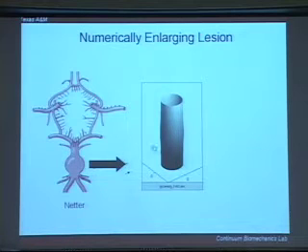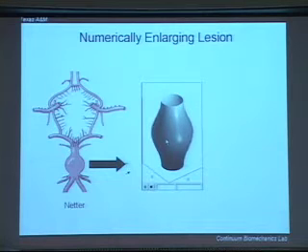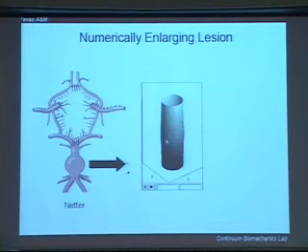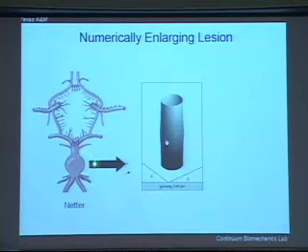So if this video will work, again, this is an academic exercise where we're looking at an idealized case where we initially remove elastin from the wall and have an associated loss of smooth muscle. We know that elastin sends an important biological cue to smooth muscle to be anti-apoptotic. So all we've done is removed a small amount of elastin and smooth muscle, and then we ask, what would the vessel do if it were to try to maintain constant the tensions in the wall, which, as Charlie mentioned earlier, tends to be very conserved across species and also vessels? And the answer is it will start to grow. It will start to enlarge, similar to, again, a textbook type of problem.